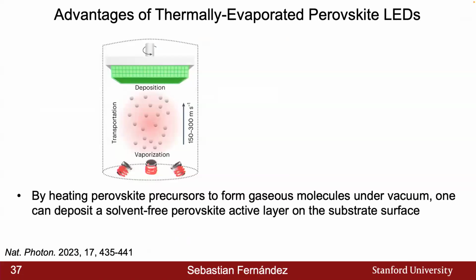Now there are a lot of advantages with this type of deposition technique as opposed to solution processing. First and foremost, this technology is already pretty industrially compatible. This is used to make some of the organic LEDs that we use today. We also have very large device area capability; we're not limited by the centrifugal force in which we're spin coating. And lastly, we can reduce the device-to-device variability that is largely seen within spin coating.